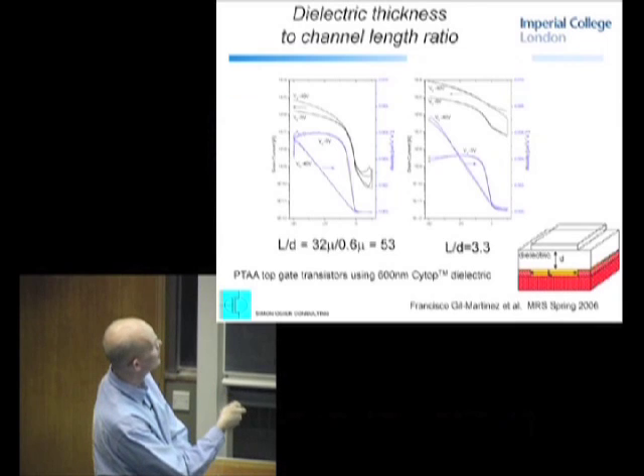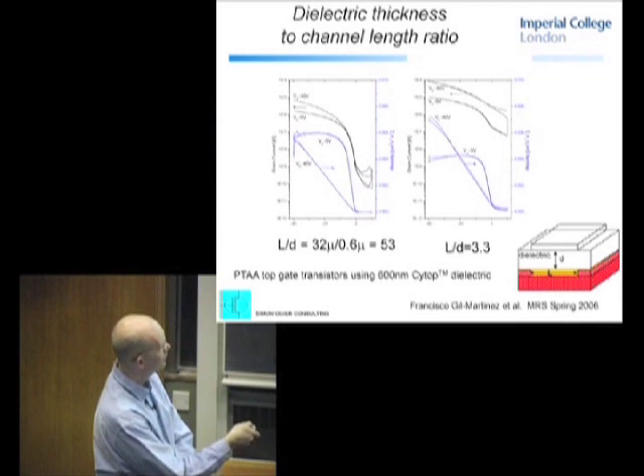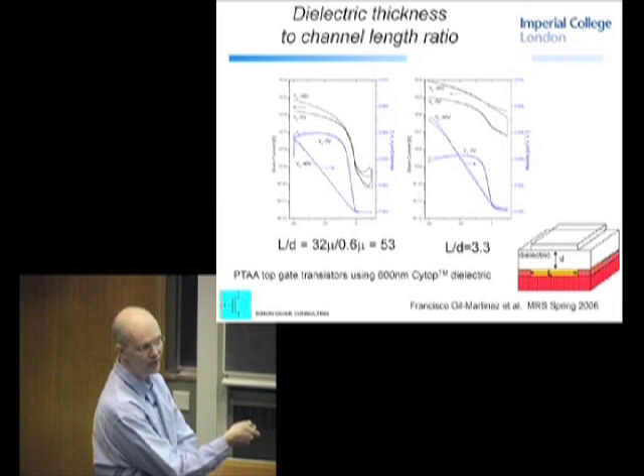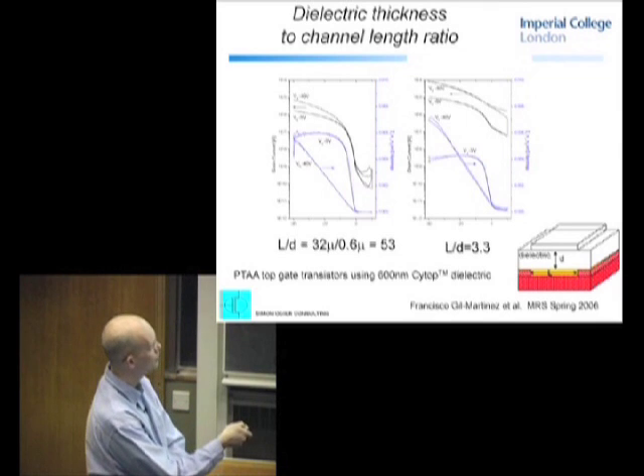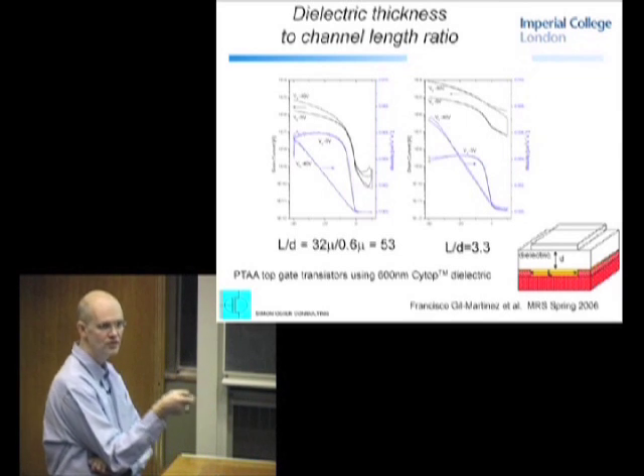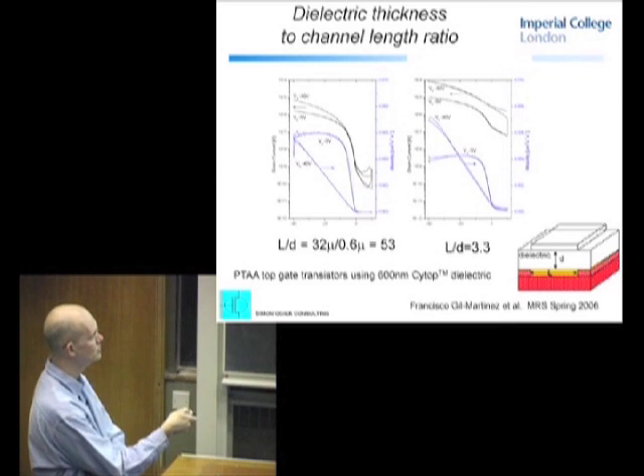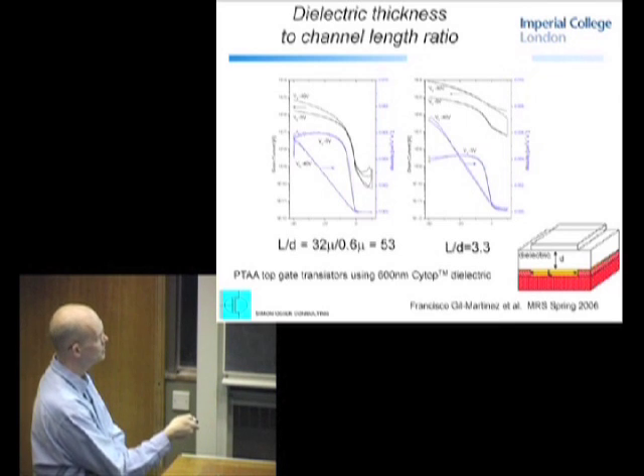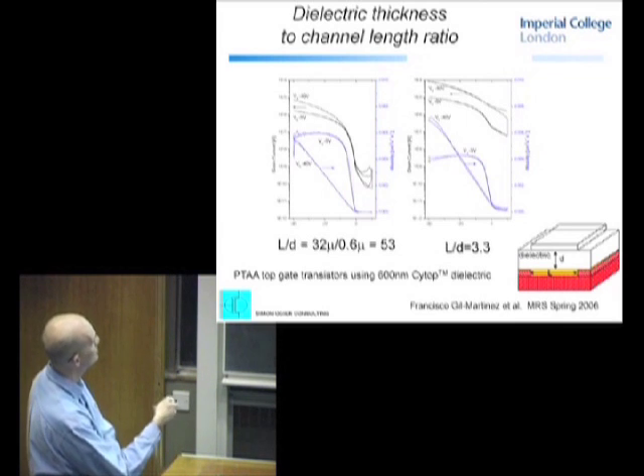There's also a scaling effect. You can't make the channel length too small without also having to decrease the dielectric thickness. So that's another reason why there's a lot of interest in very thin dielectrics. If you want to go to ultra fast switching speeds with very short channel lengths, then you have to also scale your dielectrics. And this is shown in one case.